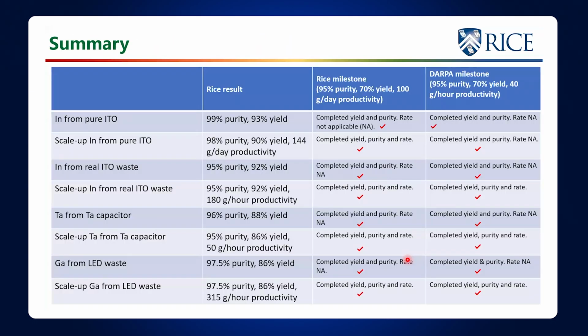So what you do is you supply to DARPA this. They tell you what you have to get. We had milestones that we put upon ourselves. This was the milestones for DARPA. They wanted at least 95% purity from all of those systems and at least 70% yield, and they wanted 40 grams per hour productivity. And so we were able to check off every box here and get the productivity that they wanted and the purity that they wanted. And so that's sort of how you do this.